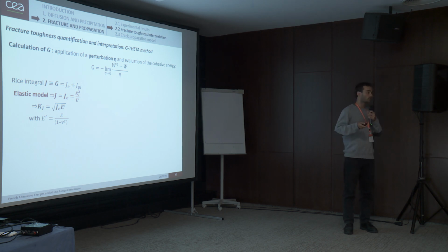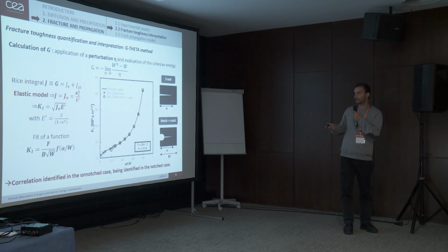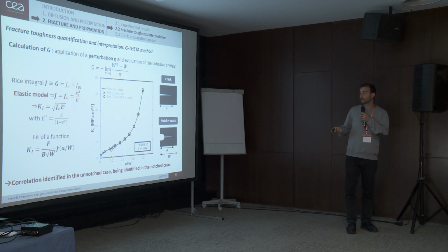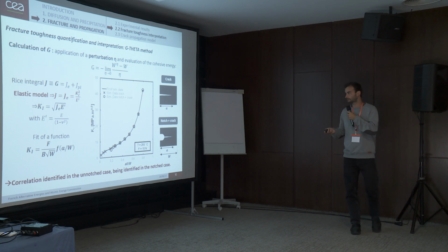But our model is only elastic, so we can easily determine the stress intensity factor, and we fit it as a function of the crack length here. So we did that for 2 cases, with a crack and with a notch and a crack. So the correlation is identified for the unnotched case, but is still being identified for the notched one.